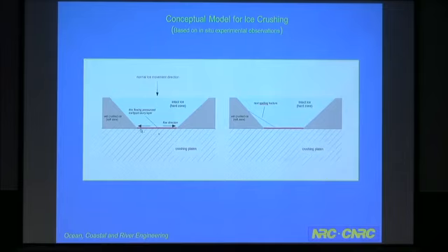Now, as this ice is moving towards the platen, you will notice that I put in a red line here. That is an indication of a thin layer of slurry. The slurry consists of about 80% solid ice particles and about 20% fluid. And it is the flow of that slurry that enables the hard zone ice, this intact ice, which I'll be referring to here as hard zone ice, to get out of the way.